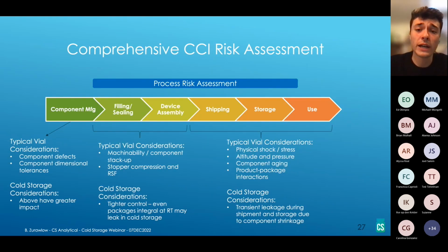And so if we revisit our comprehensive CCI risk assessment, we ask ourselves, what can go wrong at these different phases, and how do we go about controlling or mitigating those risks? And so what I've done here, just very, very high level, is outline typical considerations for vial package systems at these phases, and then what additional considerations we take for cold storage package systems. So from the component manufacturing perspective, of course, we're always concerned about component defects, deformed stoppers, etc., and also dimensional tolerances. But for cold storage, these elements have an even greater impact or risk to CCI because of what can happen at those ultra cold temperatures.